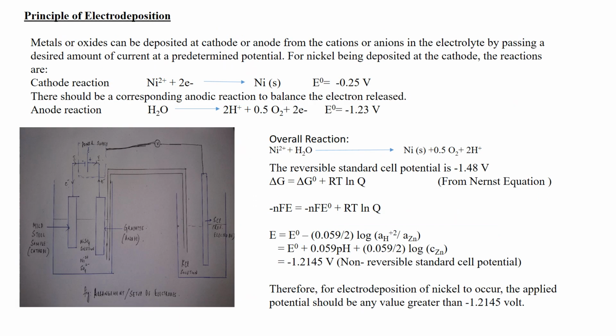Coming to the principle of electrodeposition. Metals or oxides can be deposited at cathode or anode from cations or anions in the electrolyte by passing a desired amount of current at a fixed potential. If we consider the cathode reaction given here, and also the anode reaction, the overall reaction is Ni2+ plus H2O giving nickel in solid form plus oxygen plus hydrogen ions. The reversible standard cell potential is minus 1.48 volts, and if we calculate the non-reversible standard cell potential, it comes to minus 1.2145 volts. So for electrodeposition of nickel to occur, the applied potential should be more than minus 1.2145 volts.